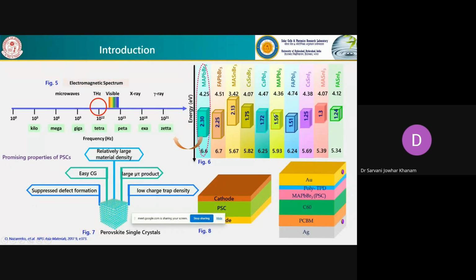The band gap suitable for solar cell application is 1.4 to 1.6 eV. Here, my research area is totally focused on higher energy radiation detection using perovskite single crystals. The promising properties of this material are that it has a relatively large material density, and we can easily grow this material in a normal environment. Not a large amount of money is required here, and no sophisticated facilities are required.